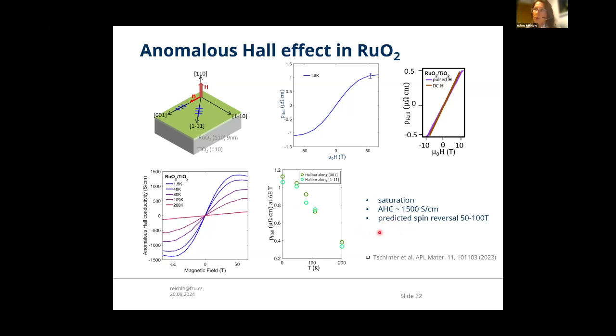We observed that the anomalous Hall conductivity here is around 1500 Siemens per centimeter. So yes, pretty large, it cannot be explained by the small net moment. Again, I would say that in the thin films it's an adventure how this will develop, whether the magnetic order is there or not. So this will only time show.